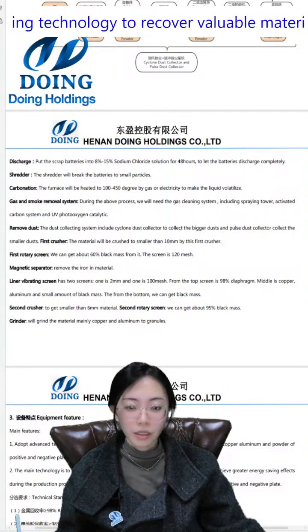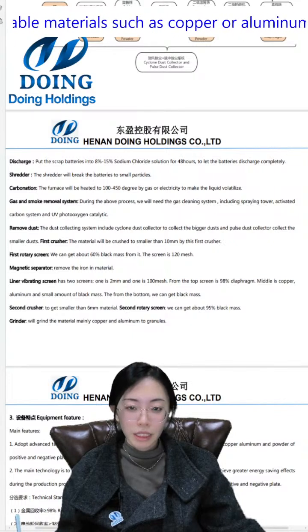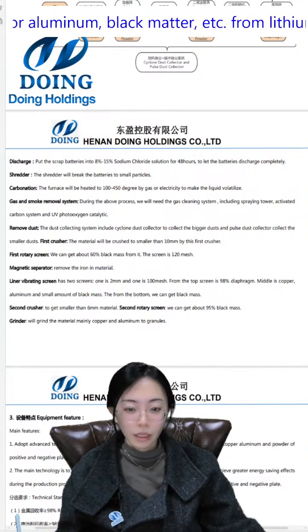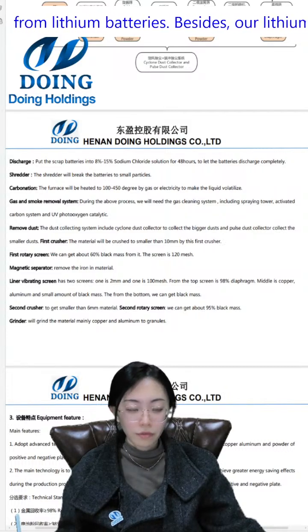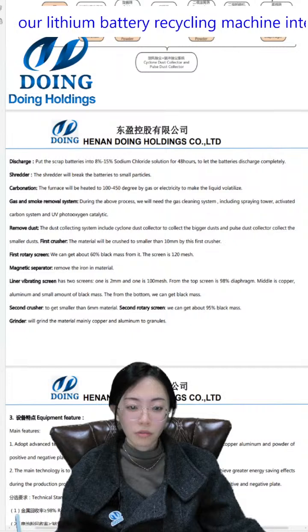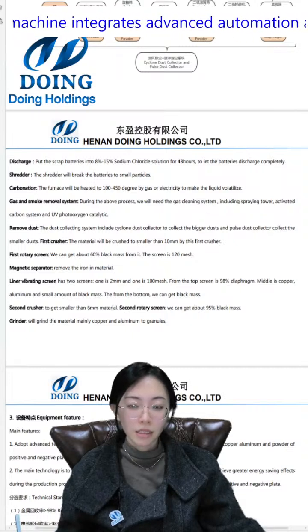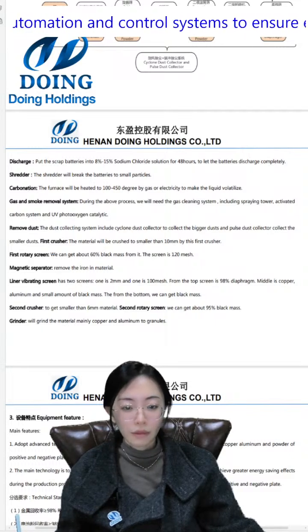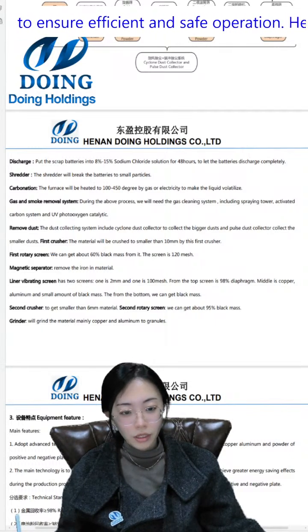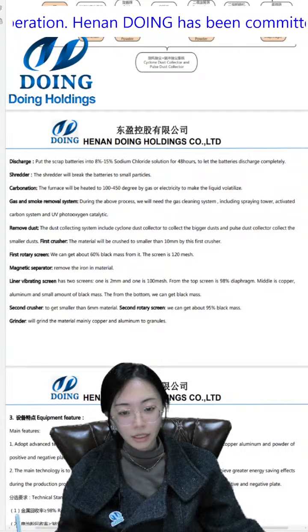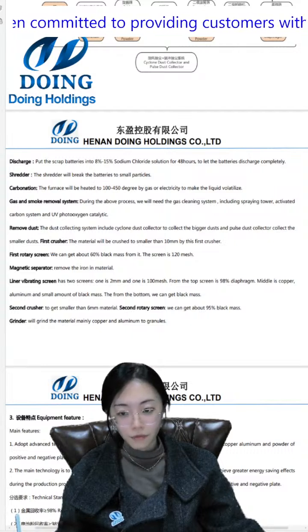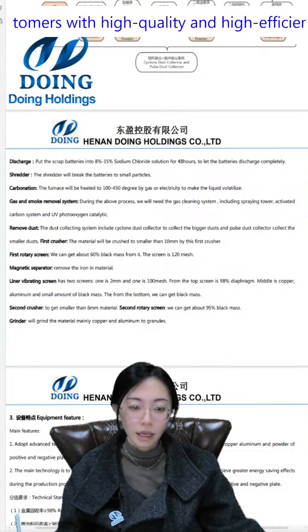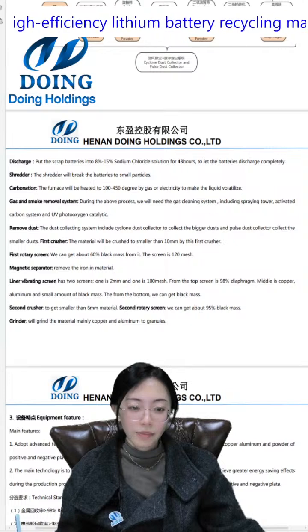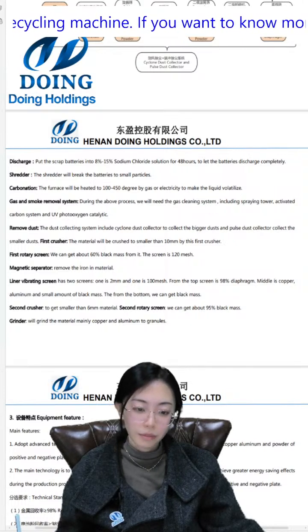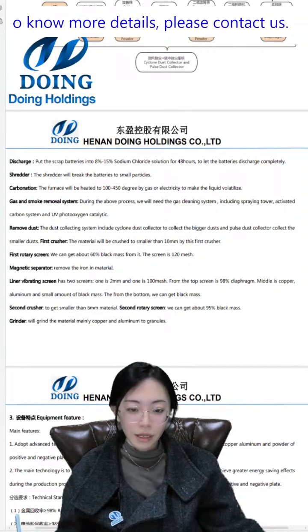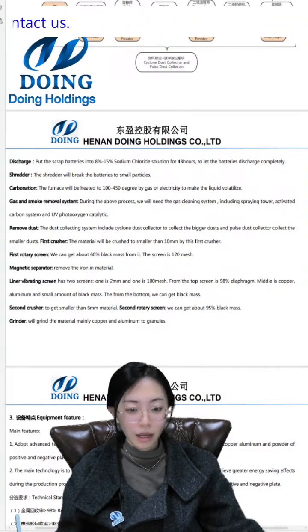And the black powder recovered here is about 60 to 70%. The first line of vibrating screen uses vibration for screening. Different products are controlled by multi-layer screens to discharge from different outlets. The two layers of the screen mesh are 2 mm and 100 mesh stainless steel. The top layer is diaphragm, the second is copper and aluminium, and the bottom layer is black powder. The recovery rate of the diaphragm is about 98%. And then the magnetic separator is to separate iron.